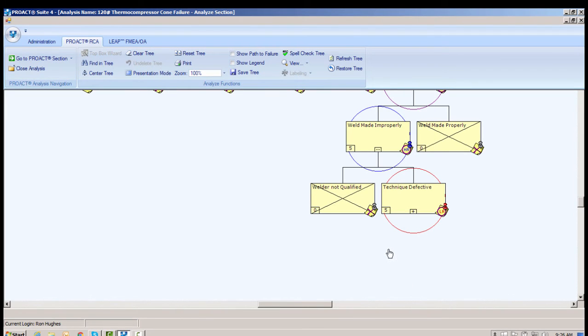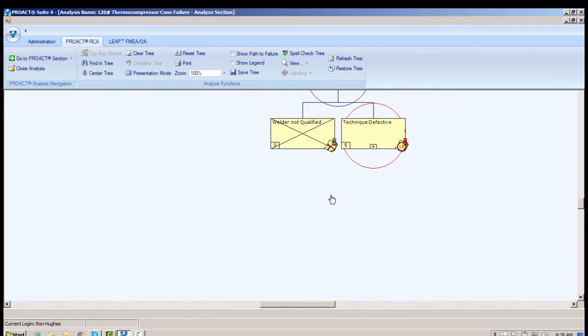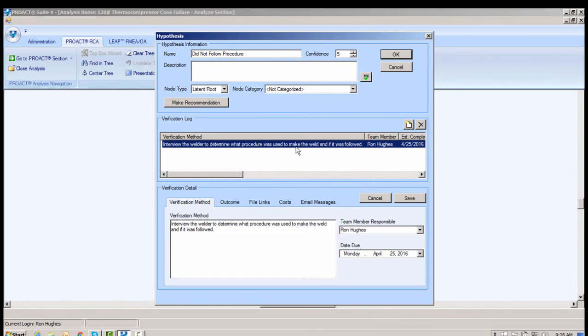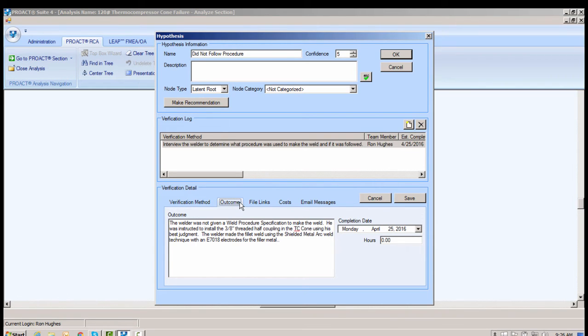What has happened here, because of all that heat that we see, the weld's been welded at about 1,000 degrees Fahrenheit, never stress relieved. Now here we say didn't follow procedure. We're actually being politically correct here. The welder didn't actually have a procedure. We interviewed the welder, and what we find is, he was told, okay, you know how to install a thermal weld, go out there and install one using your experience and best practices. So that's exactly what he did.